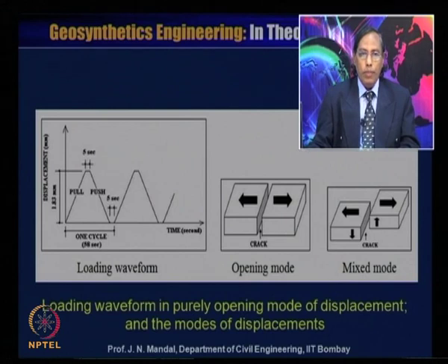So, a pull and then you obtain the displacement of about 1.83 millimeter, and then you wait 5 seconds, and then you push it, and then again wait for 5 seconds. So, this will give you one cycle, and you can continue like that with respect to time and with respect to displacement. So, this is what you call the loading waveform.